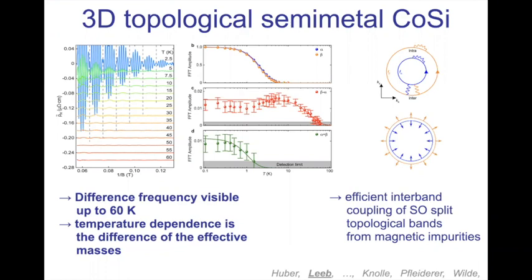Well, we have an idea, and this is if you look at the 2 orbits which give you the main frequencies, you can see that the spin density on these 2 orbits is polarized perpendicular to the Fermi surfaces. However, on different Fermi surfaces, they're polarized anti-parallel.